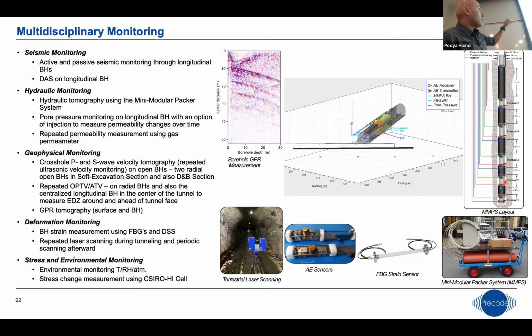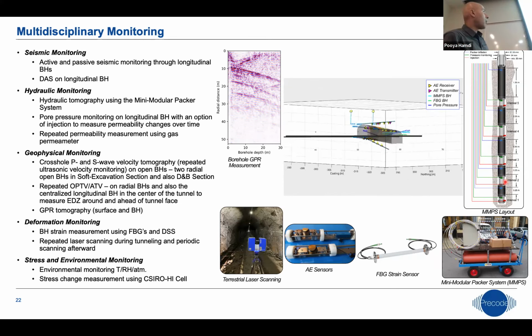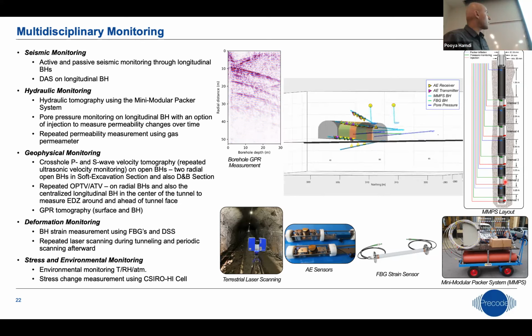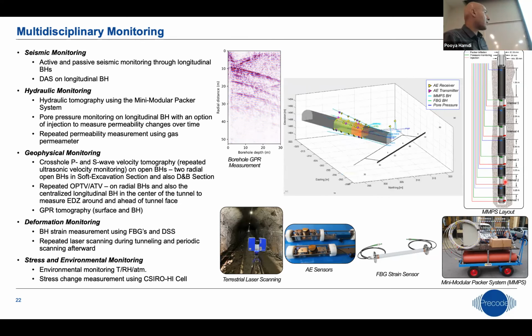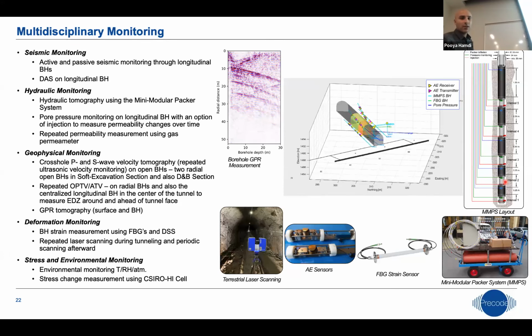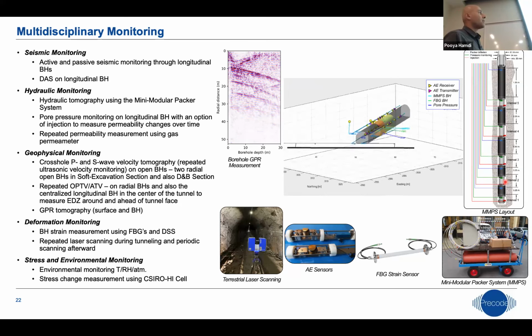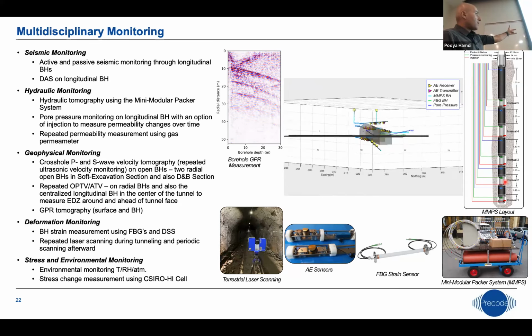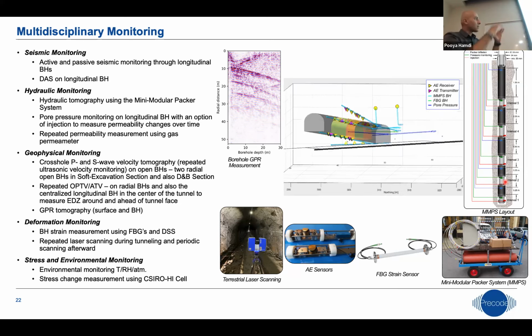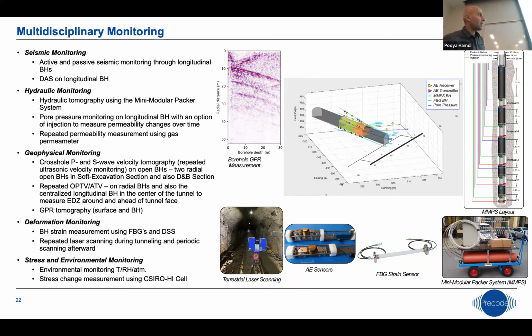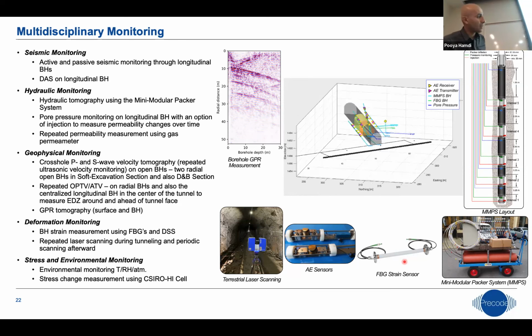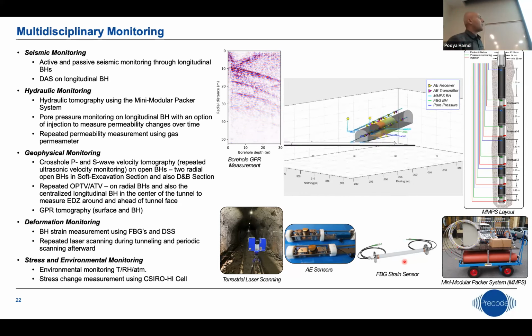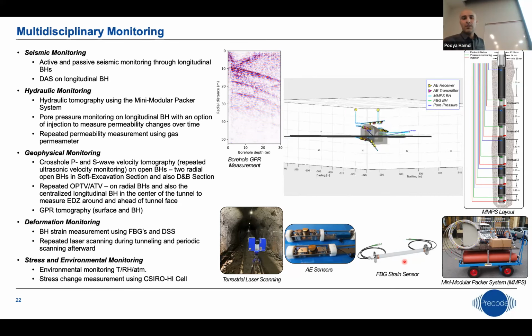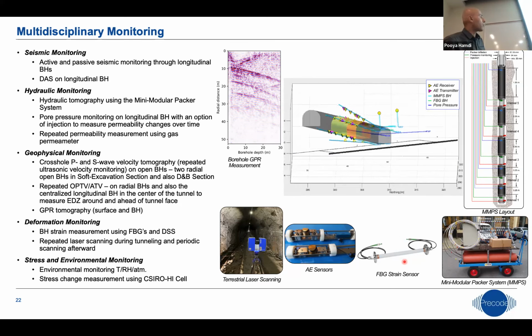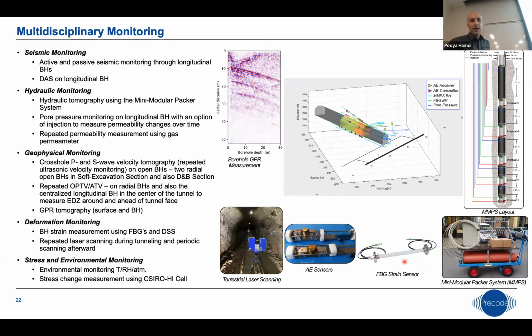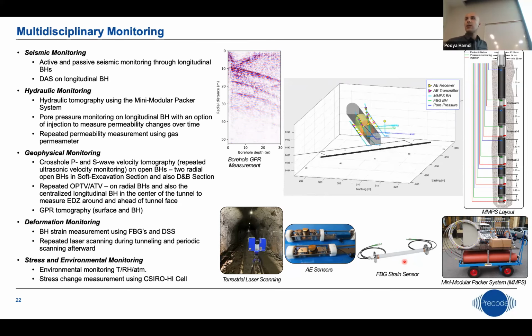And then we also have geophysical monitoring: P-wave and S-wave velocity, optical and acoustic televiewer, continuous time lapse of the fracturing, GPR or ground penetrating radar, basically non-destructive or non-invasive types of monitoring. We have a series of deformation monitoring, both in the boreholes and along the tunnel. We're using laser scanning on a regular basis, and obviously fiber optics to have really micro scale monitoring of the deformation for a couple of boreholes that we have. And on top of that, we have monitoring boreholes for stress measurement and environmental measurement.